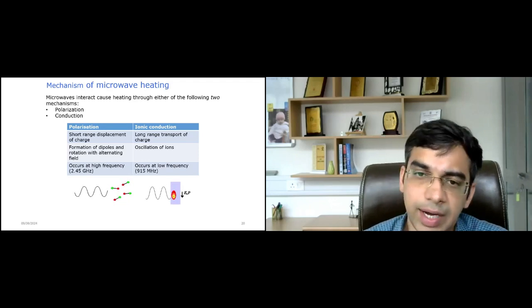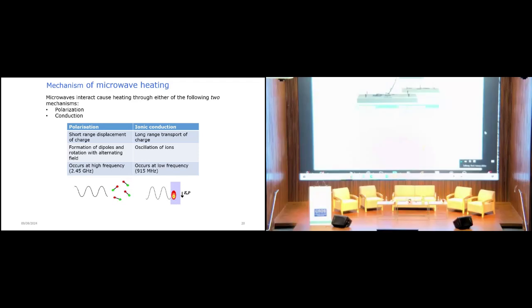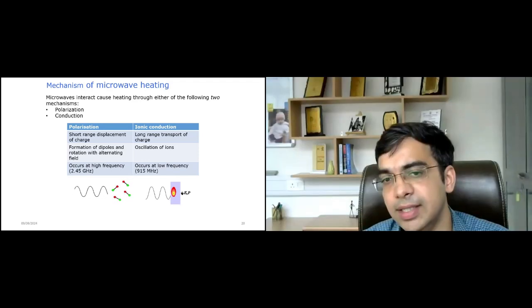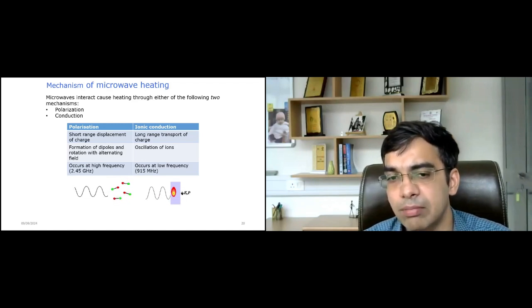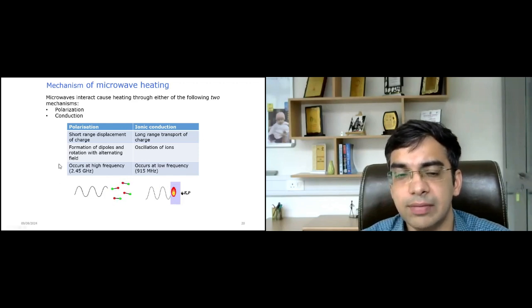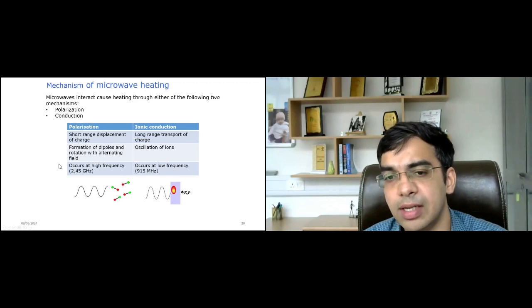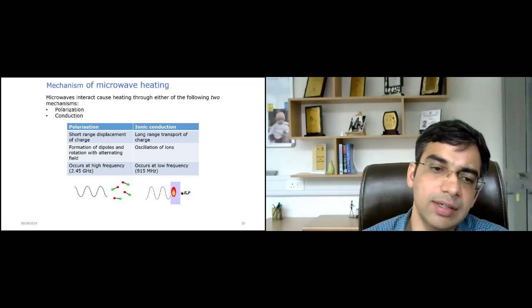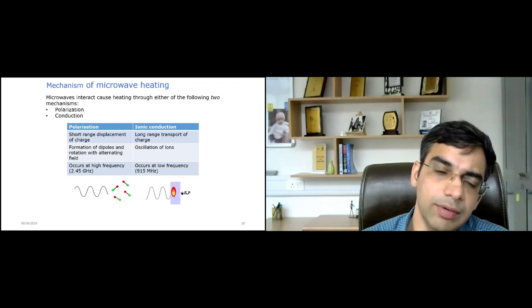On the other hand, we have ionic conduction, which is long range transport of charge. In this case, the oscillation of ions takes place relatively at 915 megahertz, which is a lower frequency. But for the sake of our discussion going forward, we will be focusing more on the polarization part, which occurs at 2.45 gigahertz. As I already mentioned, this is the frequency which is reserved for industrial heating using microwave energy in India.